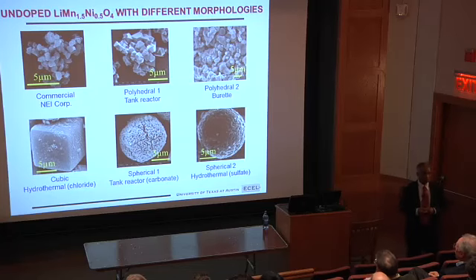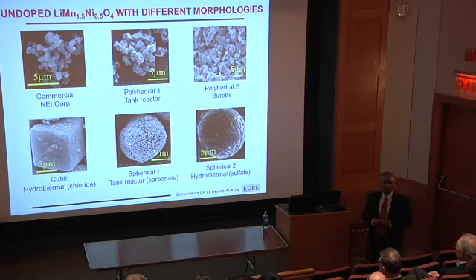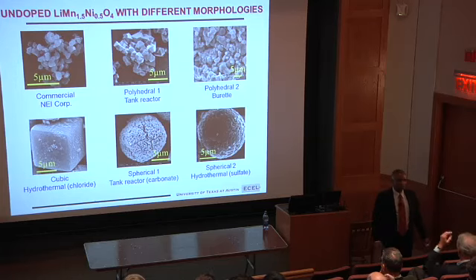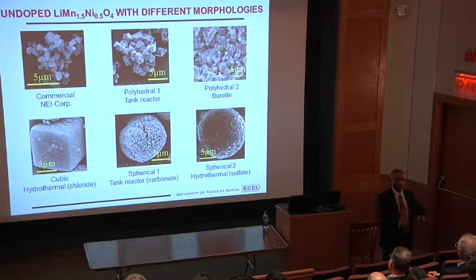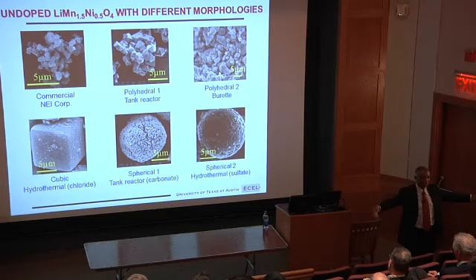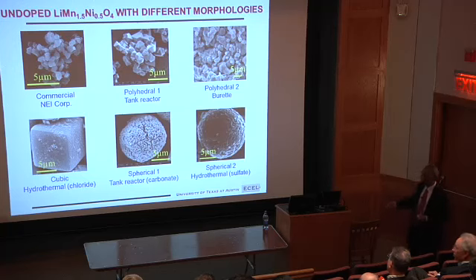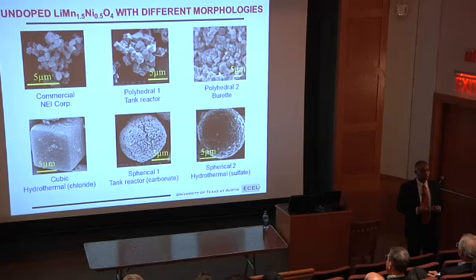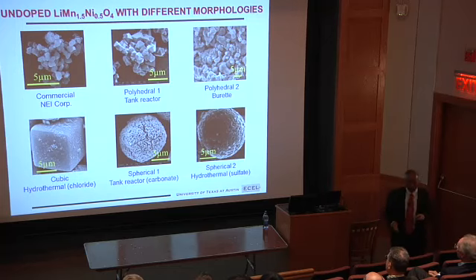We do a lot of chemical synthesis. Now, lots of times you will see reports in the literature of high performance, but it may be very porous, maybe very nano. It's not useful here. If it is very porous, very nano, I can't pack it. My car will need more space to put my battery. So the battery industry will call it tap density, how well your material is packed. So for example, when you have these kinds of particles, you may have much higher tap density as opposed to smaller particles. So synthesizing the material with optimum particle size, so you have high packing densities, is very important for cell phone, laptop, as well as for automobile. Not for stationary storage, not for grid storage.